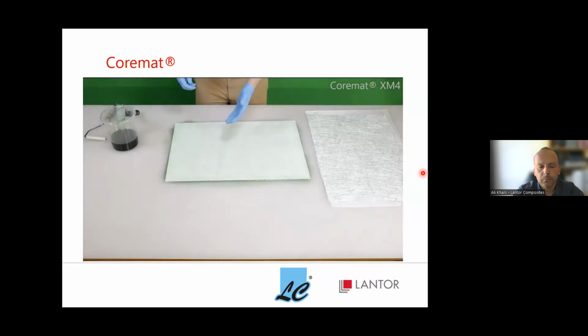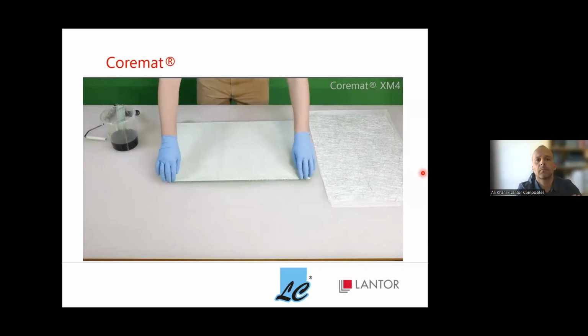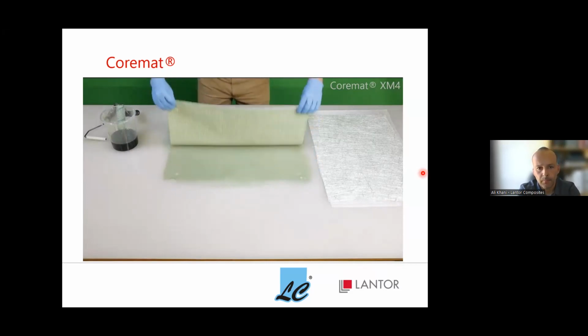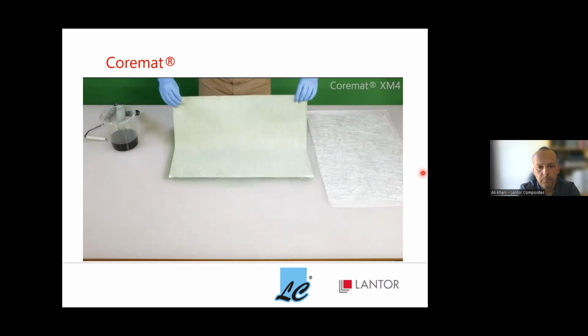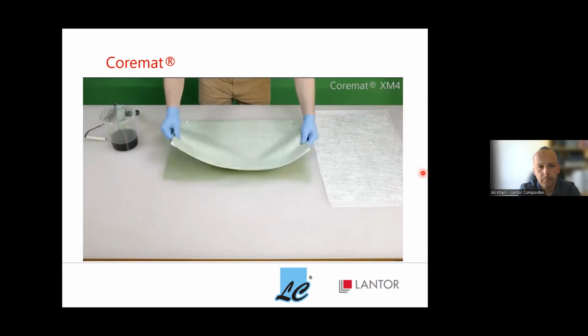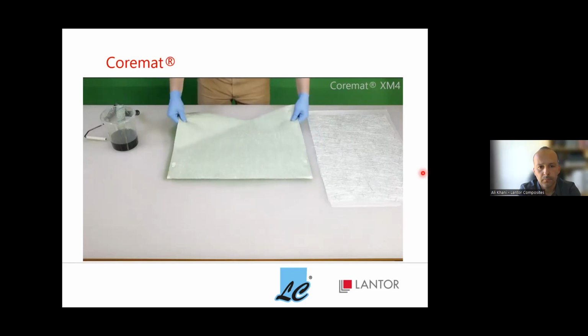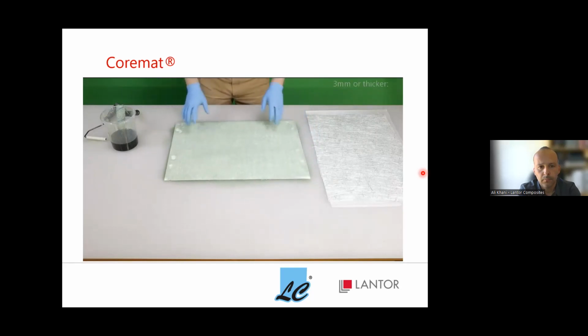See resin remaining on the surface, we can turn over the core mat to the backside and position it on the glass fiber. It should be done for all core mat products of 3mm thickness or more.